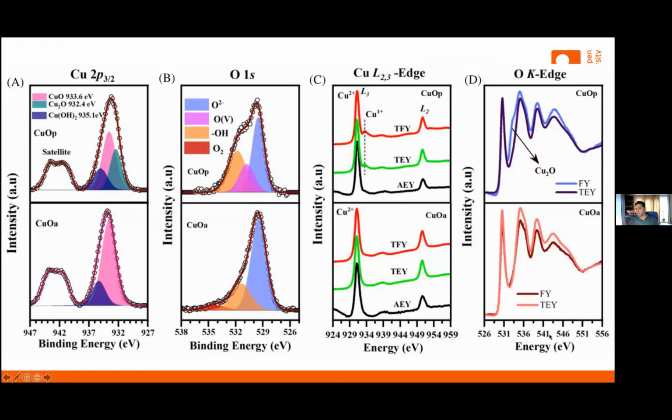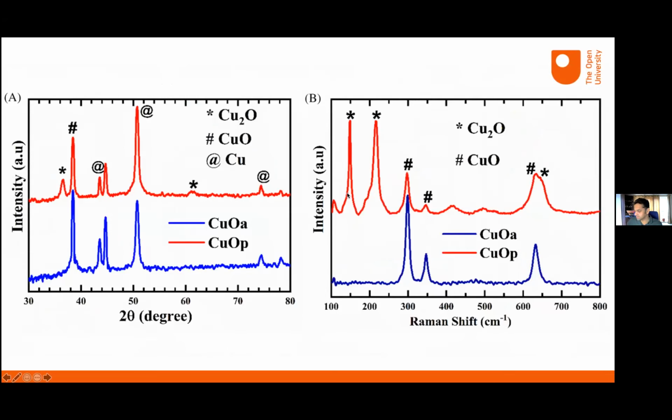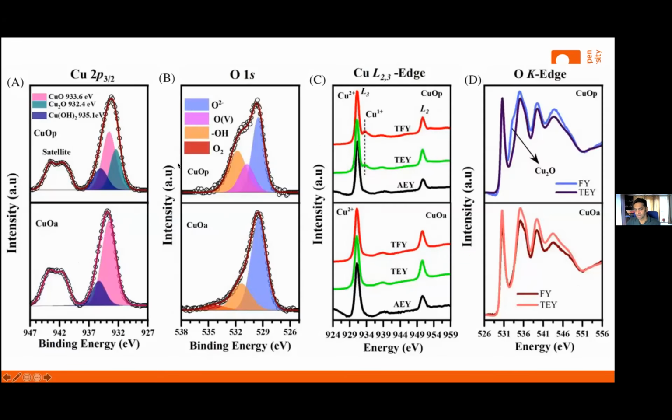This cannot be done in the lab. It has to be done in a synchrotron. The reason we are doing it in a synchrotron is that we are able to tune the energy. So this is an absorption, we call it an absorption edge. We wanted to tune the photon energy exactly to the absorption edge and map it along until the doublet splitting. That is where we need the tunable X-rays or tunable photons. That's the reason why we went to the synchrotron.